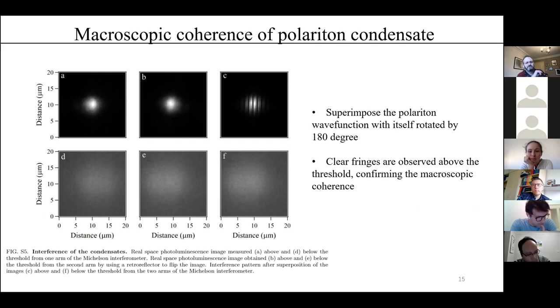Okay, thanks. Just to follow up, are the spots you see always in the same place on a given sample, or is there any time dependence? In a fixed perovskite microplate it is always at the same position. We also do single shot measurements in other microcavities, not this one, where there is no liquid crystal, and it looks like the position is not random. We do not observe any random localization of the polariton condensate. But we will try to see any such effect in the future. Done. Thanks.